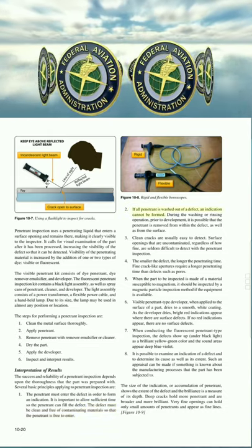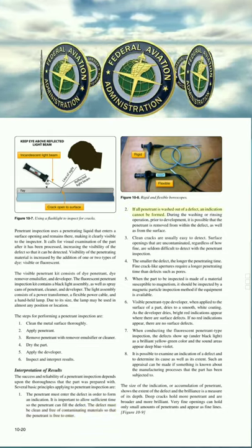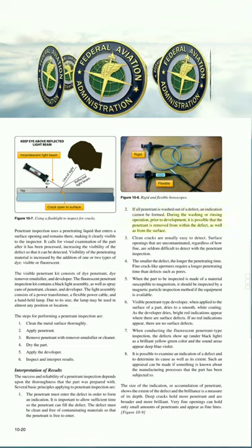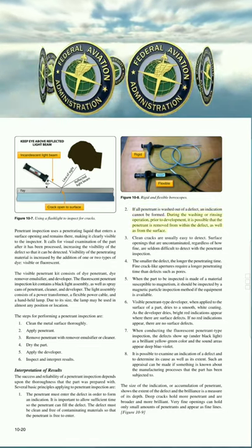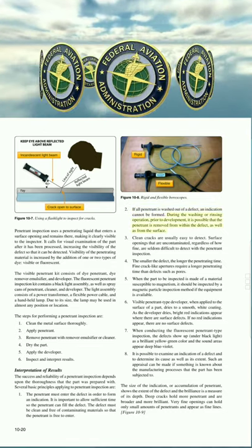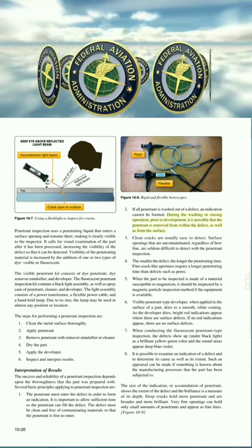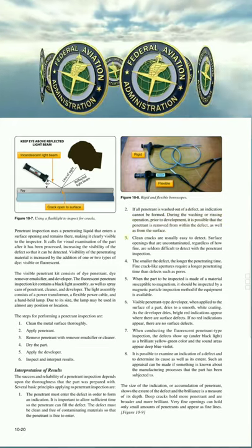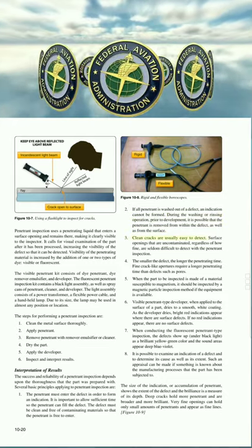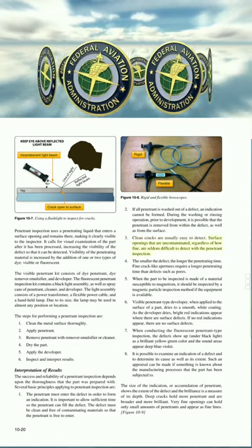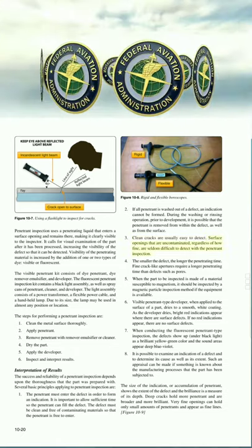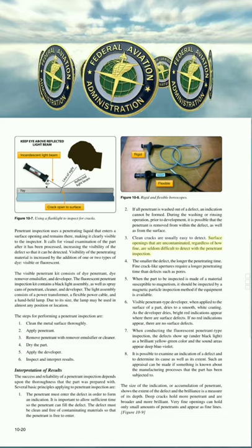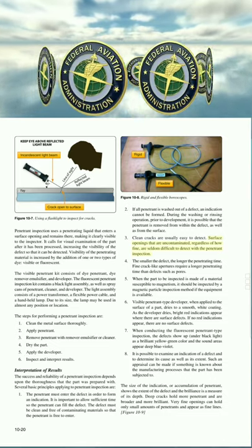2. If all penetrant is washed out of a defect, an indication cannot be formed. During the washing or rinsing operation, prior to development, it is possible that the penetrant is removed from within the defect, as well as from the surface. 3. Clean cracks are usually easy to detect. Surface openings that are uncontaminated, regardless of how fine, are seldom difficult to detect with the penetrant inspection.